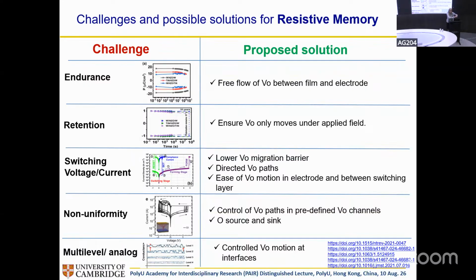So when you have your crossbar array, you can have different resistance levels. You can have different currents through there so that you have analog computing. And so getting these resistance levels to be uniform and separable, separated from each other and not overlap, is a materials challenge as well. If you look at the solutions to all these problems, a lot of them relate to control of oxygen vacancies and the motion of these vacancies through the film. So you're controlling their concentrations and controlling their motion in the material. So how do you do that is the question.